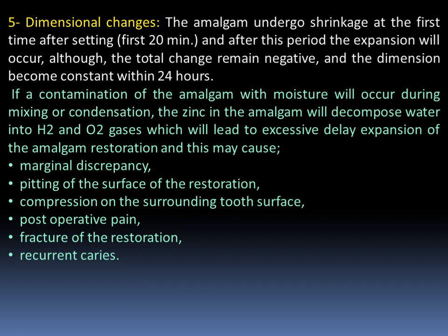Now, in case of contamination of amalgam by moisture, which can occur during mixing or condensation of amalgam, the presence of zinc in amalgam will decompose water into hydrogen and oxygen gases, which will lead to excessive delayed expansion of the amalgam restoration, and this may cause: number 1, marginal discrepancy; number 2, pitting of the surface of the restoration; number 3, compression of the surrounding tooth surfaces; number 4, post-operative pain; number 5, fracture of the restoration; number 6, recurrent caries.